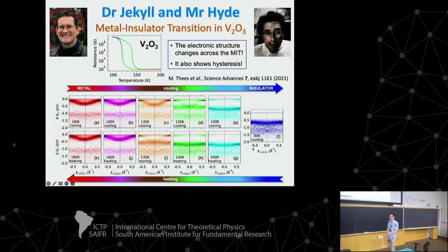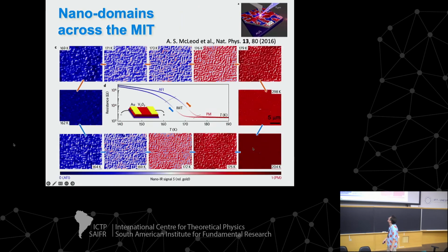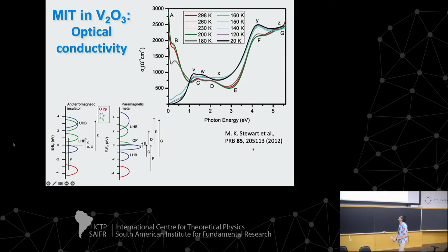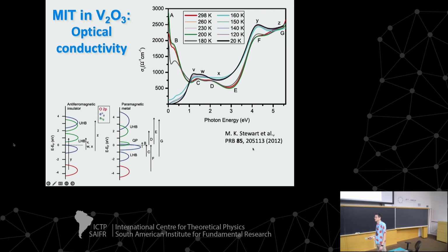Okay, we have another question here. Thank you, Andres. I wanted to come back to the results of the optical conductivity, because in those results, when it's a metal, you see the Drude peak, but then you see a hump in the gray line close to 0. You see the hump? This one? Yeah. So is this peak related to this localized state you begin to observe? How does the optical conductivity behave with temperature, and does it follow your observations of the dispersive band and the localized peak?